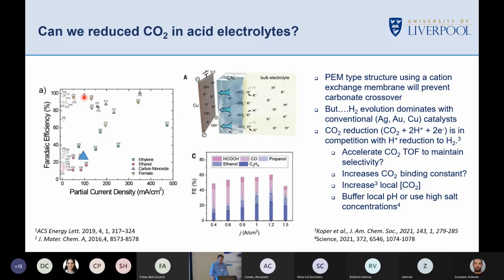So that's just the Ted Sargent work I just sort of flag up. This is probably the state of the art. This is for ethylene production. You can see that for total carbons, they're forming around about 40% Faradaic efficiencies in an acid environment by forcing up the local pH, and in this case by using a very high concentration of potassium in their system.